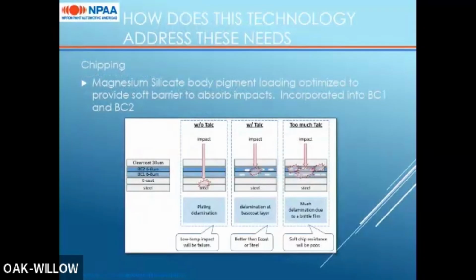So how does this technology of thin film primerless help address these needs? So for chipping, we use magnesium silicate body pigment, or talc, which is commonly used in most coatings. It is optimized for this technology to provide a soft barrier to absorb impacts, and it's incorporated into both the basecoat 1 and basecoat 2 layers.